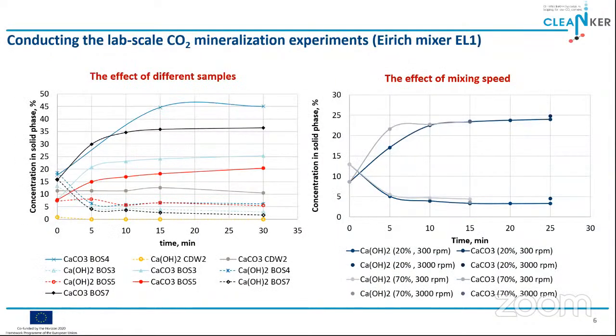So here you can see the concentrations of calcium carbonates and portlandite, and since the CO2 uptake was mainly attributed to free lime content, which is relatively high in burnt oil shale ash samples and cement bypass dust, which is not shown here, but non-existent in concrete demolition waste. As you can see, the concentrations of portlandite and calcium carbonate are not changing, as there is not enough free lime in the concrete demolition waste, and in blast furnace slag as well, which is not shown here in order not to complicate the graphs too much.